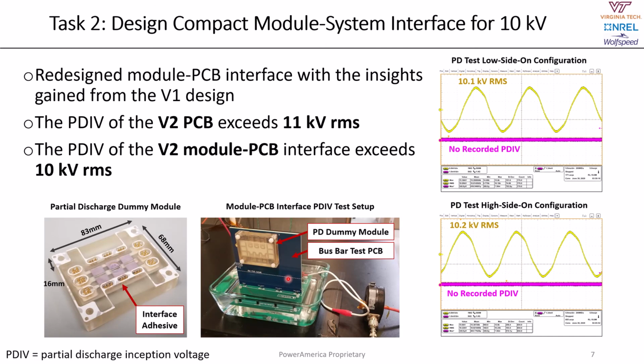And so we've taken what we've learned from that first version for the 2-die 10 kV module and have used that to improve the design for the 6-die 10,000 volt silicon carbide MOSFET power module, which is currently under development. With this version 2, the PCB itself alone has a PDIV, a partial discharge inception voltage, that exceeds 11 kilovolt RMS, and the PDIV of the module and PCB interface together exceeds 10 kV RMS.